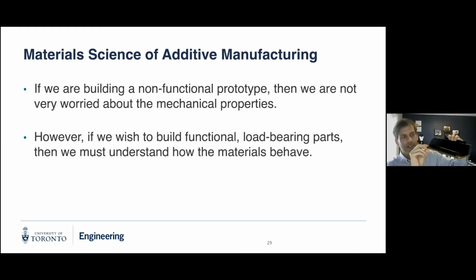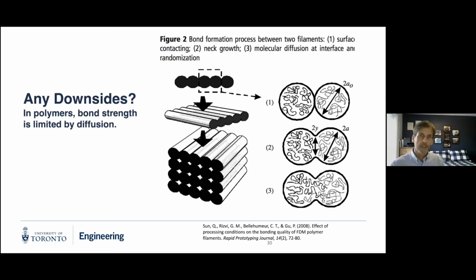So that's nothing special about that. But one thing is this part is printed in layers, and it's actually quite, I'm going to destroy it on camera here. It's quite brittle. It's not too bad in this direction, but in between the layers, they're not bonded as well as they are in the plane. And the reason for that is that we're relying on polymer diffusion. We're putting a molten bead of polymer onto polymer that's already solidified.